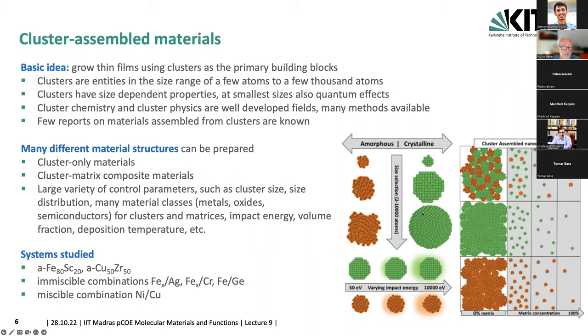And of course, you have a large variety of control parameters, such as the cluster size. So we can have different sizes and different size distributions. We can even hopefully make them atomically precise in order to preserve, for example, quantum properties in such cluster assembled materials. We can have many different materials classes, both for the clusters and for the matrix, if we have a composite material. So this could be metals, oxides, or semiconductors, for both the clusters and the matrix. We can also change the impact energy, because typically we have charged clusters, so we can deposit them in a controlled way. We can make a hard impact, like a snowball which you throw hard against the wall, or you can do soft landing and keep the cluster intact as it lands.